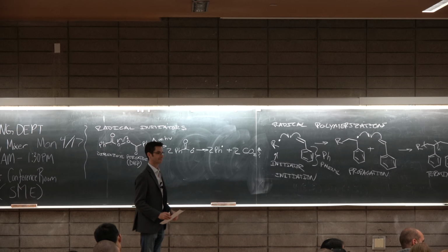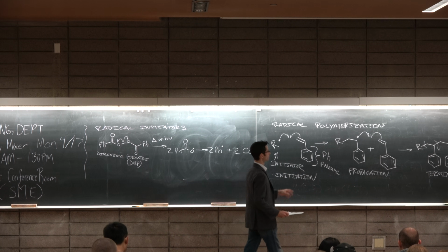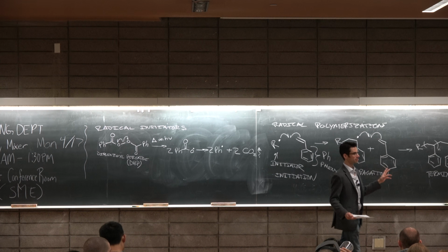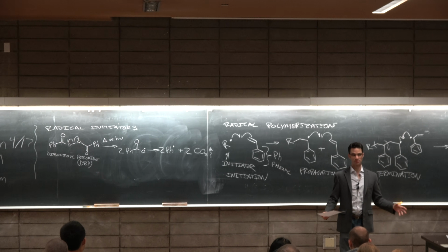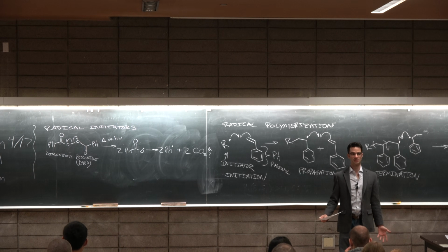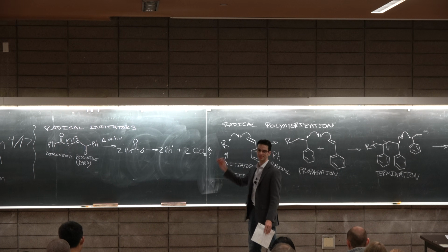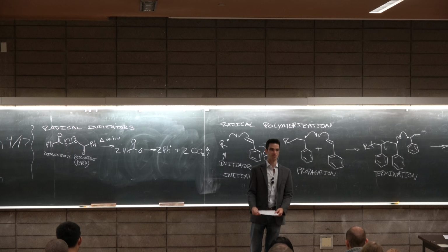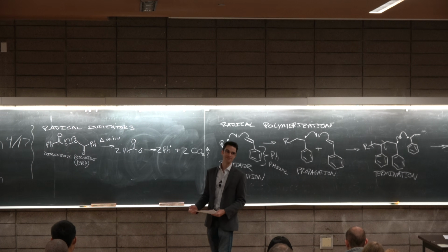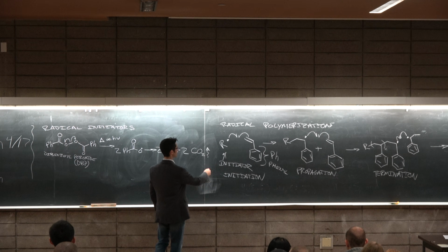Do you necessarily need to provide more heat for phenyl radicals to detach? That's a good question. So ordinarily, dibenzoyl peroxide in a lab is kept in a refrigerator, because it will dissociate at room temperature ultimately, but usually it's raised to 60 or 80 or 100 depending on how fast you want it to initiate. Yep. What's the squiggly arrow? Squiggly arrow just means bubbling off.